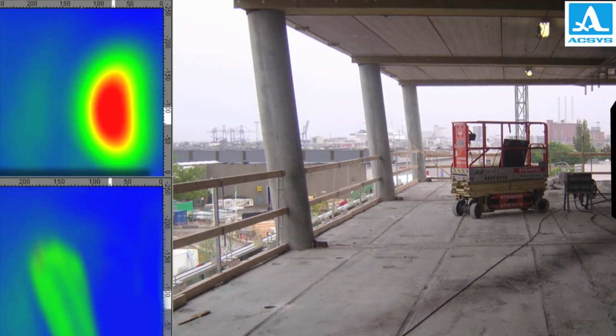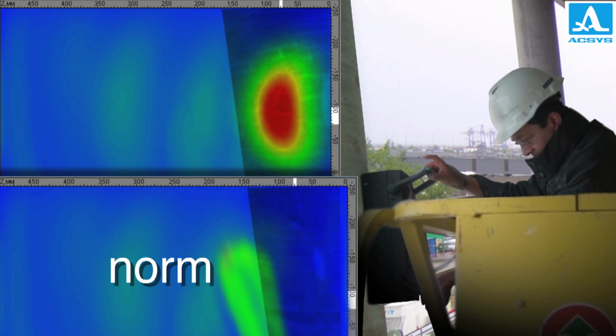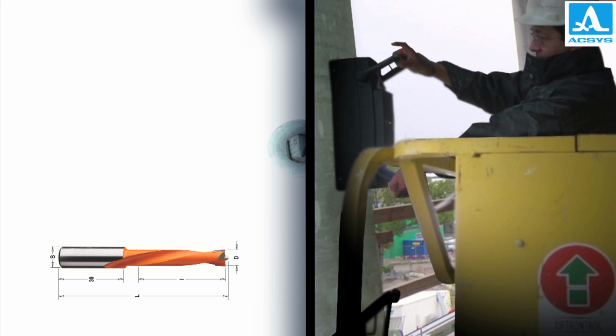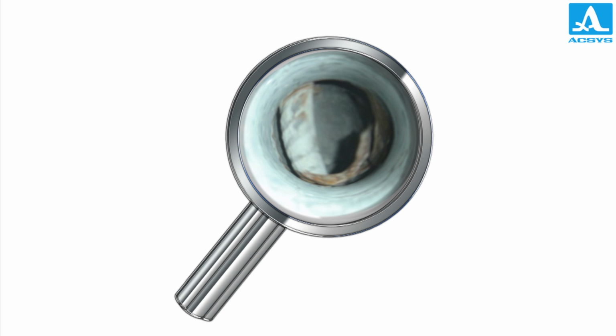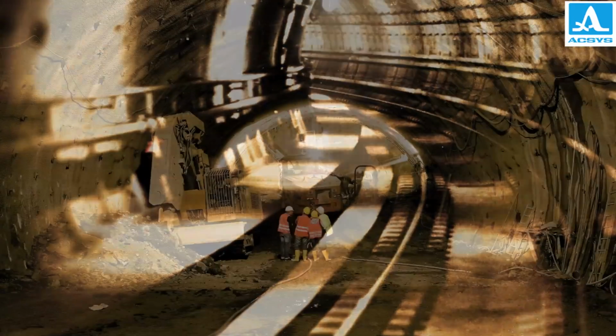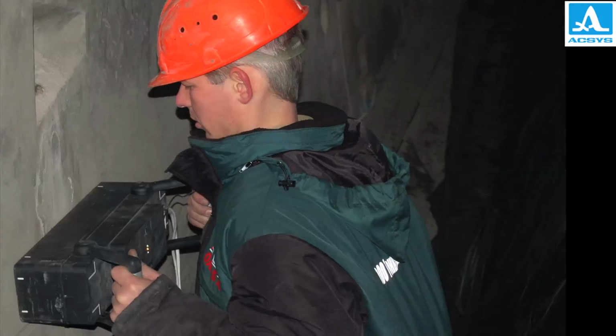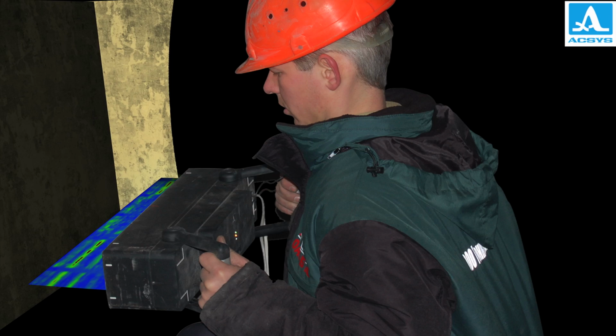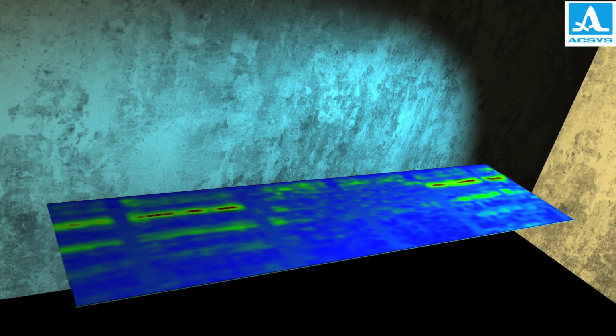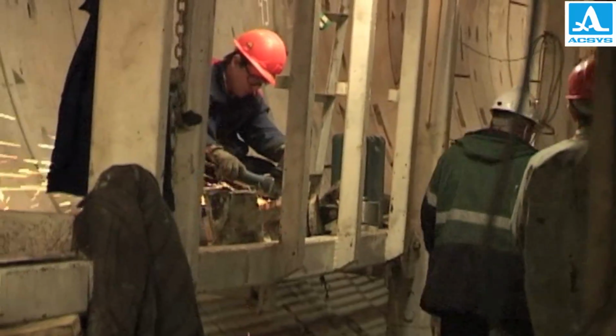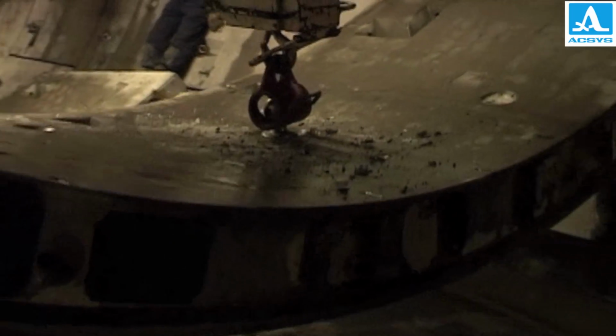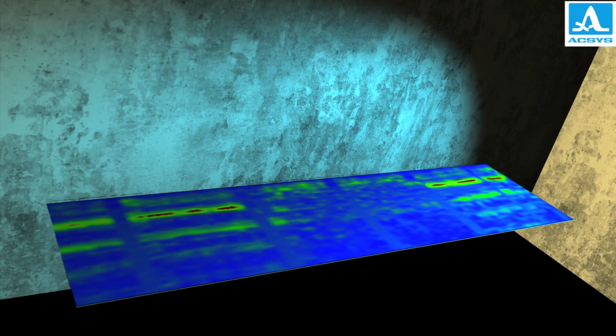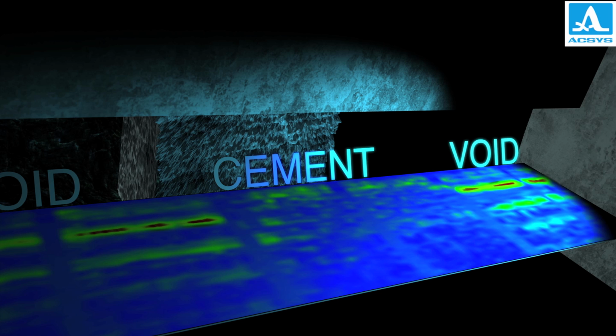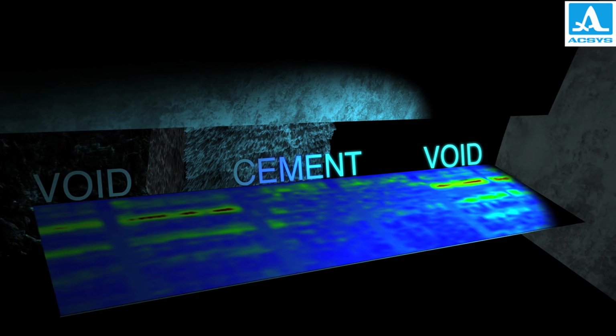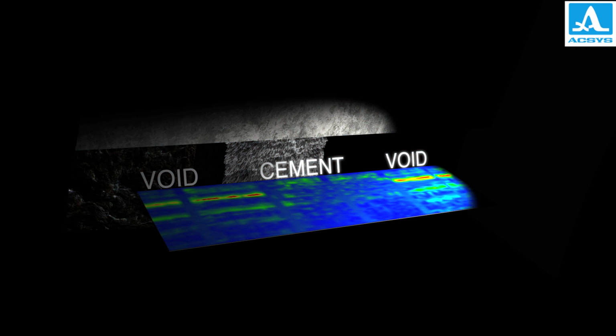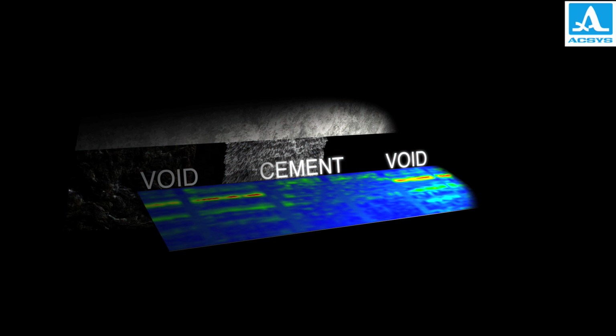The following tomogram shows a red zone corresponding to a voided steel duct in a concrete column. The test results were confirmed after performing an exploratory opening. The next tomogram shows MIRA's test results from a reinforced concrete tunnel liner. In this case, construction specifications indicated the placement of a cementitious material to fill the space between the concrete liner and the substrate. Three discernible voided zones are shown in this tomogram. At the center of the tunnel, the concrete liner is in good contact with the substrate. Along the edges, the yellow and red striped areas in the tomogram indicate potential voids behind the concrete liner.